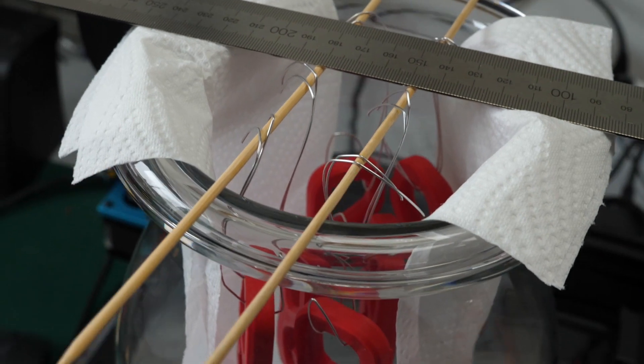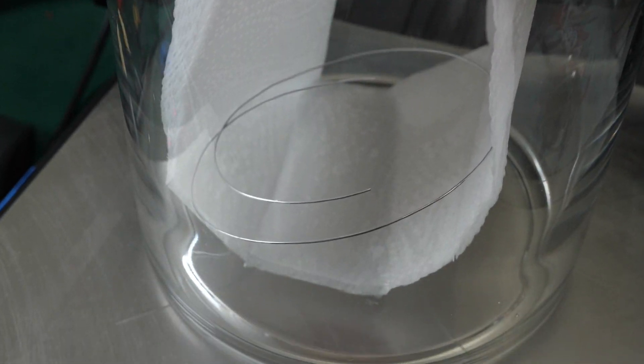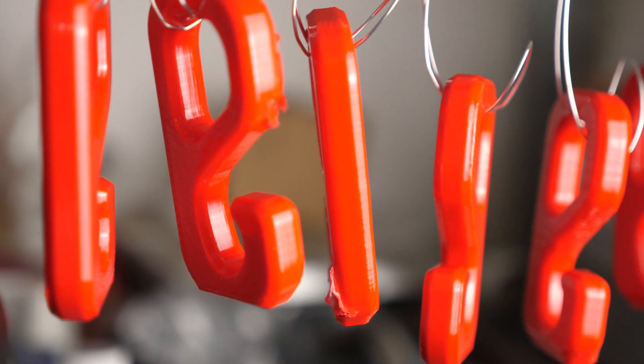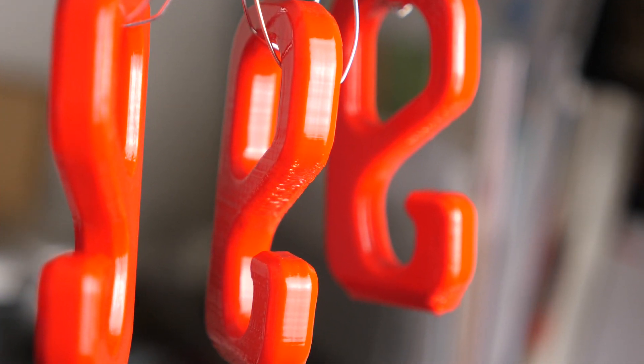Six of the 12 ABS parts were then smoothed for a good hour in the acetone vapor on one of my 3D printers. I probably should have removed them a little earlier because the smoothing action still continued a bit after they were removed from the vapor bath. Besides me touching some of the parts while removing, the surfaces looked gorgeous and shiny but I wasn't able to remove all of the rough parts of the overhanging areas.